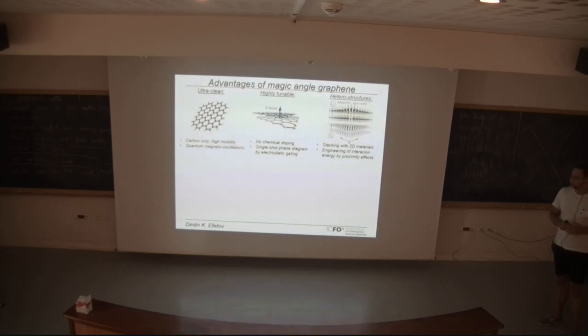The second advantage is that graphene is highly tunable. For example, with the cuprates, in order to study the phase diagram, you need to grow a lot of different crystals with a lot of different doping levels. In graphene, because it's quasi two-dimensional, we can just apply a transverse electric field effect which penetrates it. Because graphene is thinner than the dielectric screening of its electrons, we can just apply an electric field and modulate its electron density. For this reason, we can obtain phase diagrams in one single shot in one device just by tuning the electric field across it. We don't need to grow different crystal species and measure them all separately. And last but not least, it was developed over the last 10 years that we can readily integrate graphene into heterostructures, such as these van der Waals heterostructures, and I'll talk a little bit more about it next. We can manipulate it by hybridizing it with other materials and really control its intrinsic energy scales by proximity effects and so on.